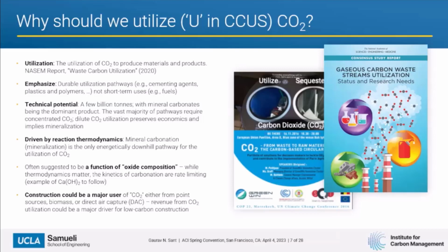And depending on where you land, the technical potential is somewhere in the vicinity of about 3.5 billion tons. That's the largest quantity of CO2 that you could use. And the vast majority, in fact, is in building materials. Why? It's really driven by reaction thermodynamics. Mineral carbonation, the idea of taking CO2 in the gas phase and turning it into a solid, is really the only energetically downhill pathway for the utilization of CO2. Really important thing to keep in mind.